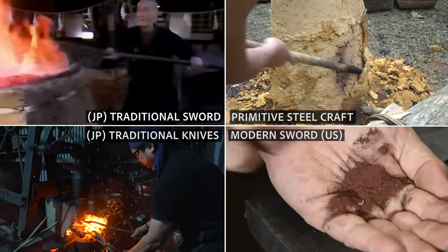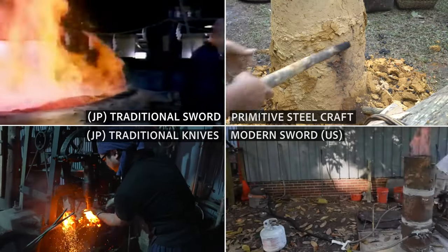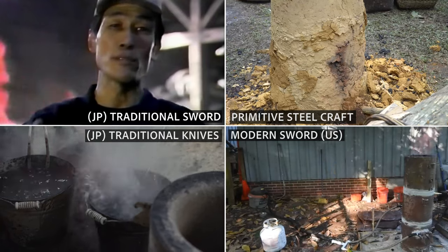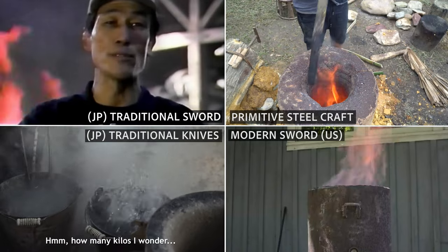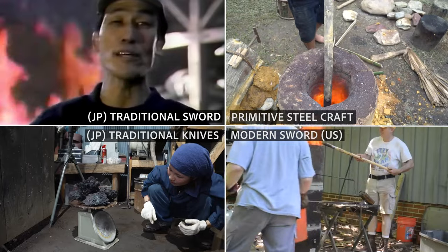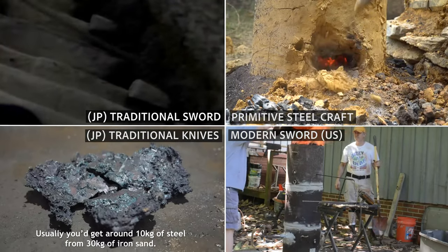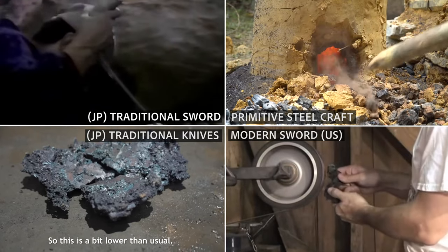The other grade of steel, low carbon and pure iron, reacts in different ways as well, so it was easier with the right amount of carbon to figure out how much carbon was inside. Before sending the various pieces of steel and iron to blacksmiths, they were usually consolidated by hammering. The pieces were heated until they were red and then hammered. This process allowed further improvement of the purity of the iron or steel since the slag trapped inside is squeezed out.